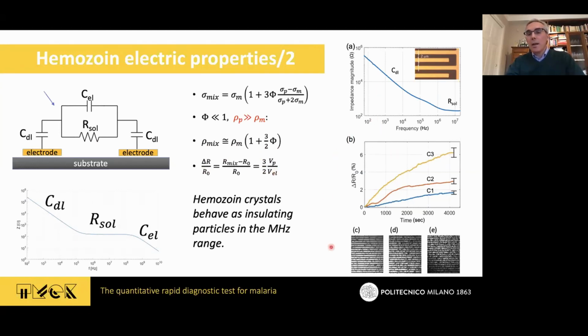In order to do that, we made some experiments in which we dispensed different concentrations of hemozoin crystals on top of some interdigitated electrodes that you can see here, and working in the plateau of the conductance corresponding to this region here, we were able to detect an increase of the resistance. It's a good solution, because we find that also at 1 megahertz, hemozoin crystals are resistive enough to be distinguishable from the medium. And for the infected red blood cell, there is no problem, because it is well known that cells are really insulating up to the gigahertz, which means that 1 megahertz is good enough.